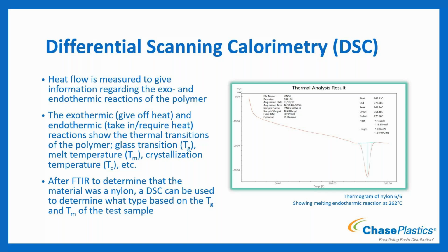And so when the crystals are able to start breaking apart, that'll show as an endothermic reaction, and you'll see a peak for that. And then crystallization temperature, if you run it through a second one, it'll show your recrystallization temperature, T sub C. So as you're cooling it off, when it will start to crystallize.